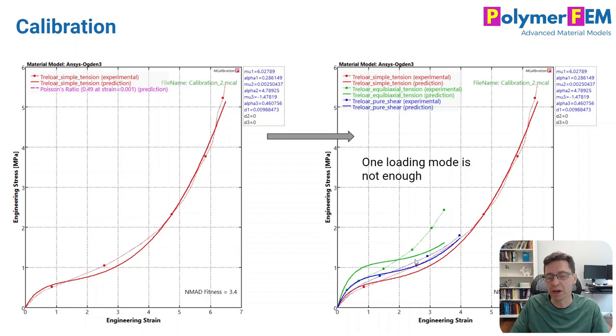But then if I take that material model and see what does that model do, when I compare the predictions to the known results for biaxial and shear, we see that the model doesn't work very well at all. The errors are very large under those conditions. So what this means is that you can't calibrate the Ogden model to use tension data, uniaxial tension data, and then expect it to work in anything that's different than uniaxial tension. It doesn't work.